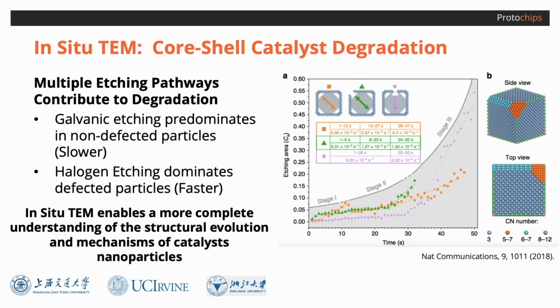The nanocubes that had a pristine platinum shell structure with no defects underwent a slow galvanic corrosion process, and the platinum shell remained structurally intact after etching away of the palladium core, and consequently, they retained their catalytic activity.